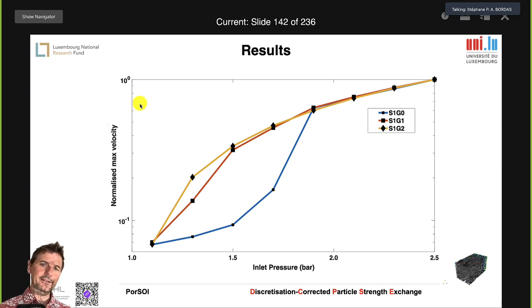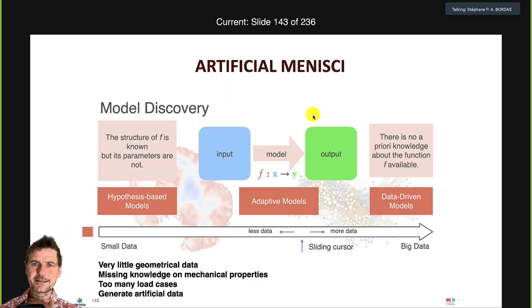And what's really interesting is that in the normalized maximum velocity, so you take the maximum velocity in the whole sample and you compare to the inlet pressure, what you see is that in the original case, you see this behavior. But in the case where you increase the porosity, you do not see this change in behavior, which means that there is some sort of change in regime, which you see only in the case of the real meniscus, which indicates that the porosity level has a strong impact on the ability of the porous material to filter high velocities. So it basically means that the high velocities are filtered out thanks to the presence of the microstructure. So this is this case study.